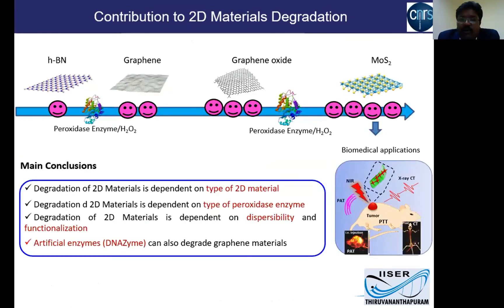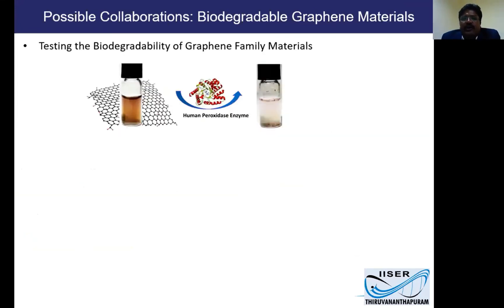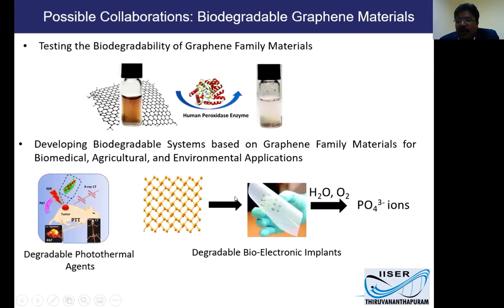In conclusion, we found degradation of various 2D materials including boron nitride, graphene, graphene oxide, and molybdenum disulfide. MoS2 appears highly degradable compared to graphene oxide, while graphene is more degradable than hexagonal boron nitride. Understanding degradation kinetics is essential for planning successful clinical implants. I am also working on bioelectronics using black phosphorus, a semiconductor that is also a degradable material, and welcome collaborations in checking the degradation of 2D materials.